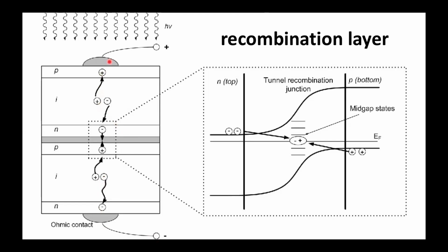The positive charges go the other way, but these, in between, they meet. So they have to recombine. So you have a special oxide layer where the plus and the minus recombine. And that means there have to be equal amounts of positive and negative charges that meet there. So that's the current matching. There has to be an equal amount of positive and negative charges for them to recombine efficiently. You'll also call it a tunnel junction, a recombination junction.